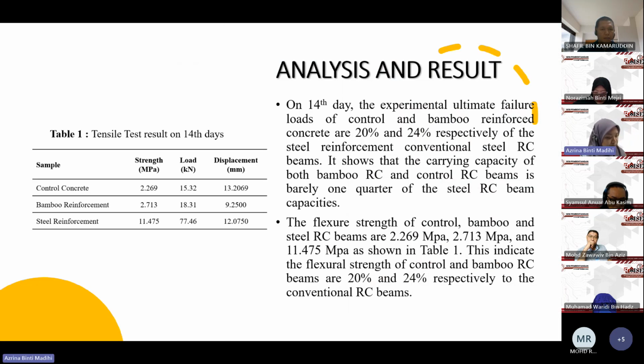For the result analysis, on 14 days, the experimental ultimate failure load of control and bamboo reinforced concrete are 20% and 24% respectively of the conventional steel RC beam. It shows that the carrying capacity of both bamboo RC and control RC beam is barely 1/4 of the steel RC beam capacities. The flexural strength of control, bamboo and steel RC beam are 2.269 megapascal, 2.713 megapascal, and 11.475 megapascal as shown in table 1. This indicates the flexural strength of control and bamboo RC beam are 20% and 24% respective to the conventional RC beam.